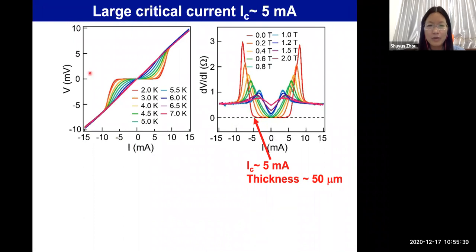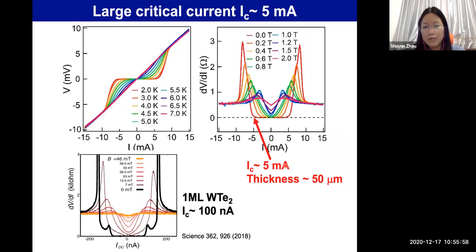We can also take the derivative of this VI curve, and we can get this partial density of states. And here we can see that at zero magnetic field, this critical current is as high as 5 milliamp. This upper critical current is much larger compared to the monolayer tungsten ditelluride, where the critical current is about 100 nanoamp. So we know that our intercalated sample has many layers stacked together, and our sample thickness is about 50 micron. This tells us that we basically have many layers of superconducting molybdenum ditelluride, and these different layers are very weakly coupled.